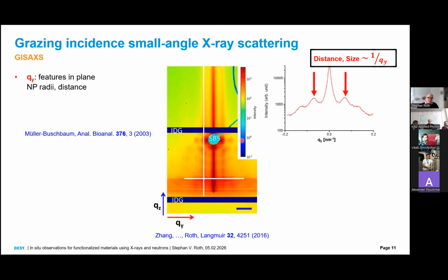And in order to analyze it, we make so-called cuts. We make a horizontal and a vertical cut. In the horizontal cut, if you follow this, you see a strong peak in the middle. This is called the Yoneda peak. I will come to it in a minute. And you see these maxima, and this is like Bragg scattering. It's a pseudo-Bragg peak. The position of this Bragg peak is inversely proportional to the real space distance. And then we can get out from this cut features in the sample plane like nanoparticle radii and distances.